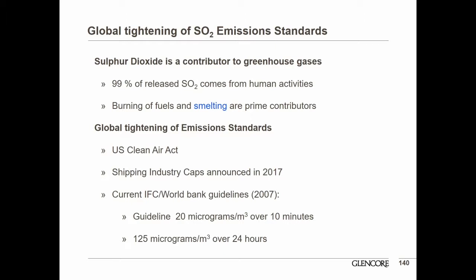You can see on the slide there the current IFC World Bank guidelines of 20 micrograms per cubic metre over a 10-minute period and 125 micrograms per cubic metre over 24 hours. These are extremely stringent and they require modernisation of a lot of the existing smelter networks around the world, and any new smelting technology needs to have a very inherently safe design, and a design that is able to capture these days over 99.8% of the SO2 that's emitted, and that would be considered world's best practice.